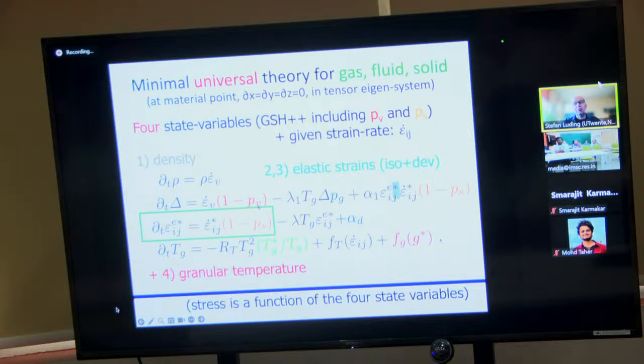If you have no plastic events, you are purely elastic. If you have only plastic events, there is nothing remaining here, so 1 minus 1 would give you 0. Okay, and then you have relaxation dynamics. Tg is the relaxation rate, and it's proportional to itself. So this term, the time derivative, and this term gives you exponential relaxation, as I mentioned in the previous part